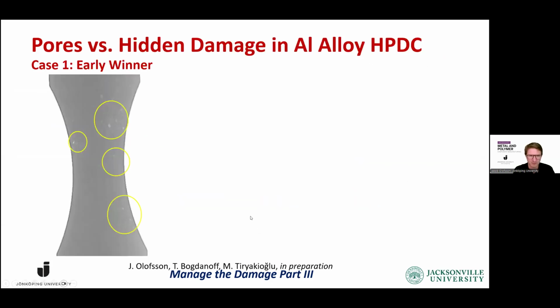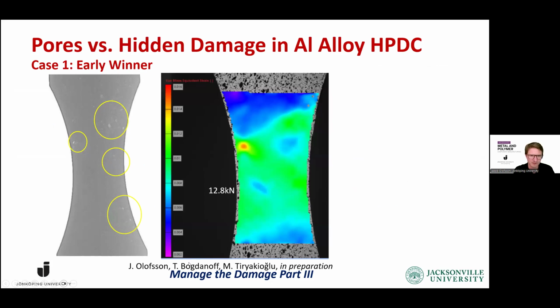So again, we have a case 1 here, which we call an early winner. You can see from this X-ray sample here that we have several pores within this sample. So when we take a look at the strain field during the load here, at a certain load, you can see that there is a clear strain concentration, which is also associated with the left porosity area. The porosity area in the central part is also subjected to a higher load, but it doesn't turn out fully as clear as the other one on top.